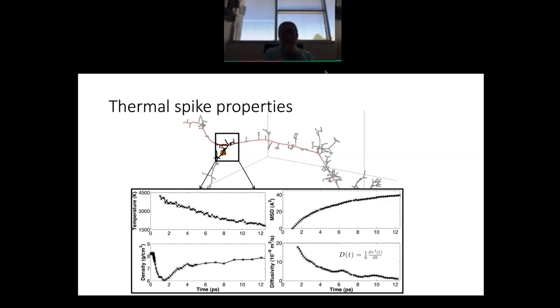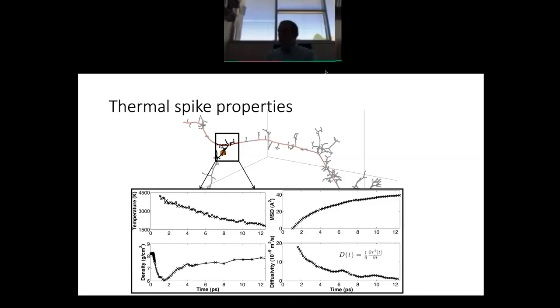There's another question from Arthur Tim. Is the effect of electronic stopping and electron-phonon interaction in metallic glasses not significant? Well, electronic stopping is definitely significant. As with crystals and metals, it's especially significant at higher energies, right? Electronic stopping is actually present at all energies. I should be more precise about this. It contributes to energy loss by the particle or by PKAs at all kinetic energies.